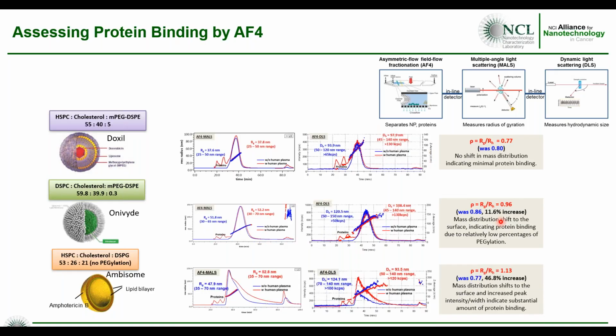If we look at Onivyde, we conduct the same type of experiment, and we calculate this shape factor again. We can see there's a slight increase, about 12% upon incubation with human plasma. So this suggests there might be some protein binding to the surface. And as you can probably expect with AmBisome, if we look at the shape factor here, it's almost a 50% increase, implying there's a lot of protein binding to the surface.